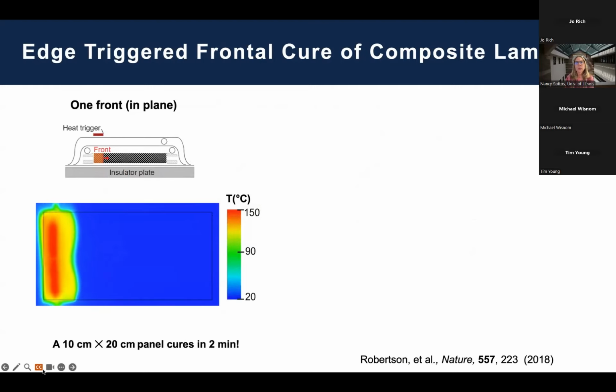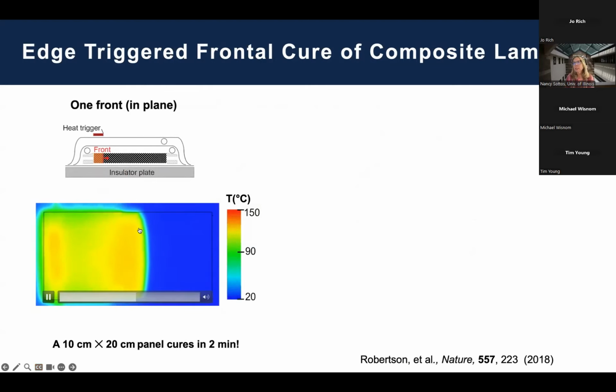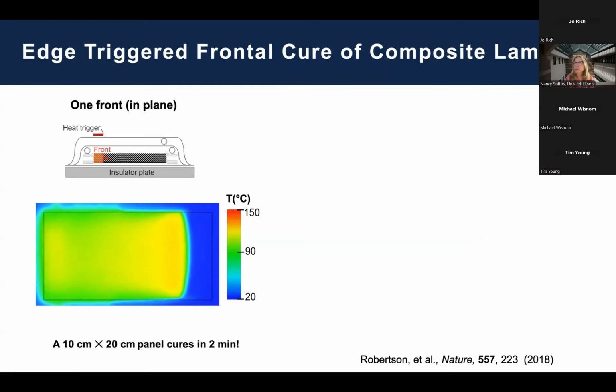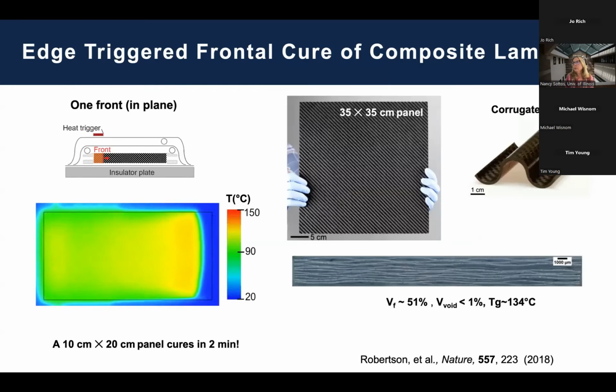That's the trigger. Now there's just a little bit of energy added in. It's actually 5 seconds the resistive heater is on. And then that's enough to locally heat it and propagate this front. This is kind of dramatic as we propagate the front along the panel, but that's the way we did it first. And you're able to cure this panel in 2 minutes. We've made up to 35 by 35 centimeters. And you can get kind of complex shapes. You can have the front travel along a corrugation in the flat panel. I just show a cross section there.